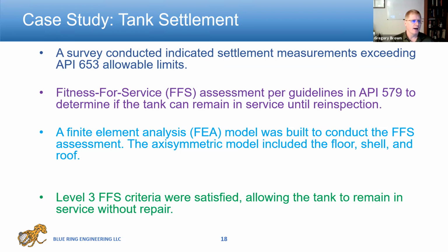So basically what's happening is the edge of the tank is actually dropping down. So the soil underneath it is settling. This is causing the tank to deform. What does this do? This causes higher stresses in the tank, and it may not be safe to leave in service. So since it did not pass the 653 requirements, we went to API 579 and did fitness for service.